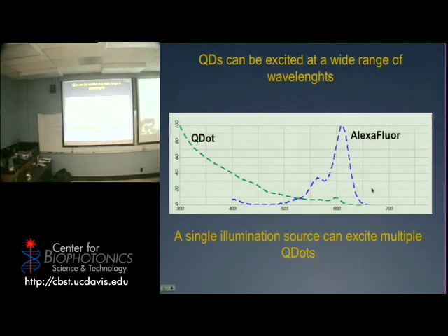Exactly. And as you can see, especially here, which is the range where you will want to pump light in, the absorption is actually minimum. If you want to heat them up to some extent, you have to heat up here, but here is closer to the UV, so there's not a lot of penetration. So in actuality, they do heat up to some extent, but not nearly as much as gold does. So quantum dots are not helpful for photothermal therapy. Gold is good. Quantum dots are good for other things. Think more imaging.